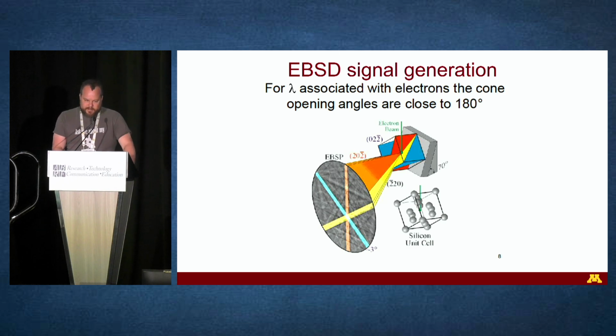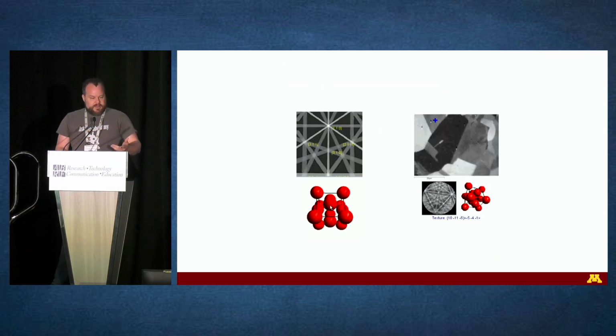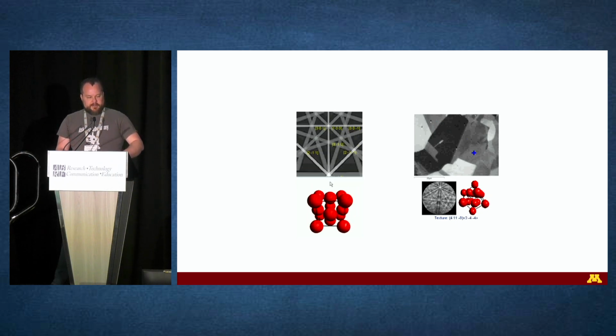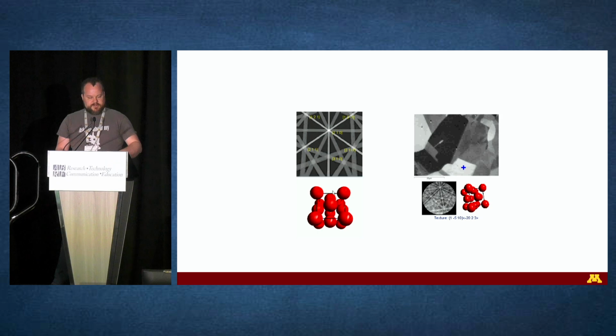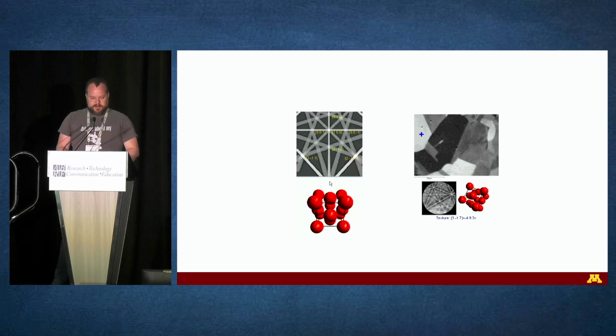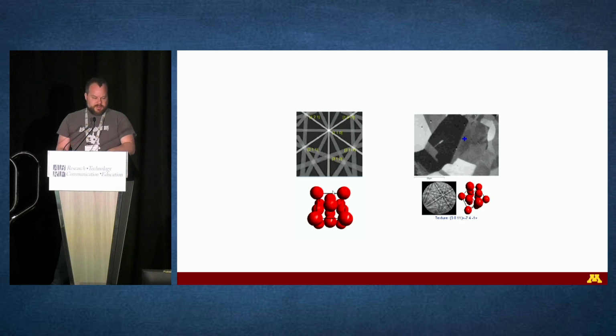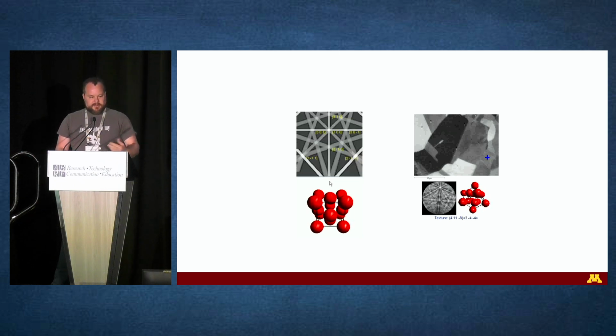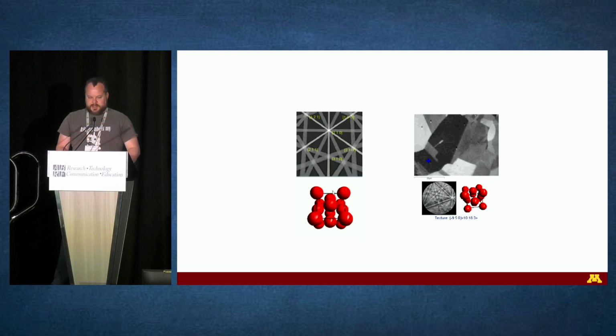EBSD, electron backscatter diffraction. This is the technique I specialize in. It's used quite extensively in material science and geology. But essentially, we shoot the electrons in at a very shallow angle, and we can collect a diffraction pattern out. And the diffraction pattern is actually the direct projection of the crystallographic planes in the material. If we take a model and we spin the unit cell around, we can see how the pattern would look, so we can model what every angle should look like. And therefore, when we point the beam at a crystal, we can collect the diffraction pattern, and the computer can then recreate which orientation that crystal is.